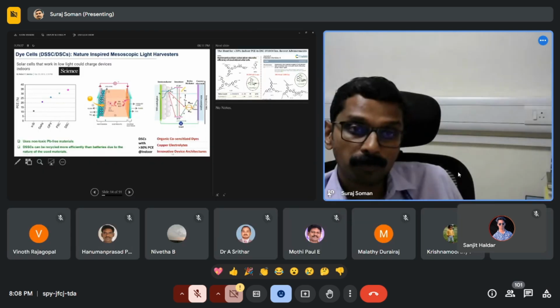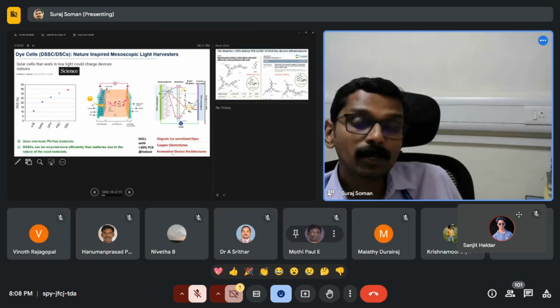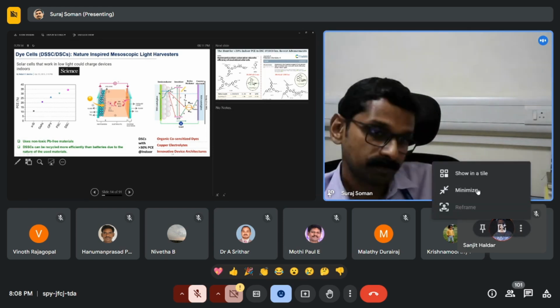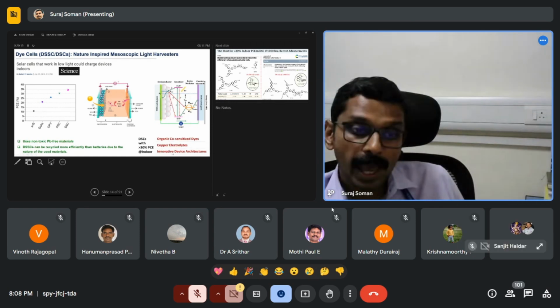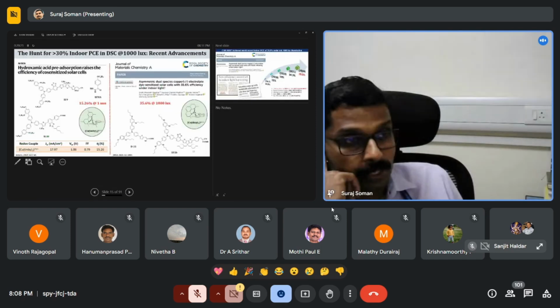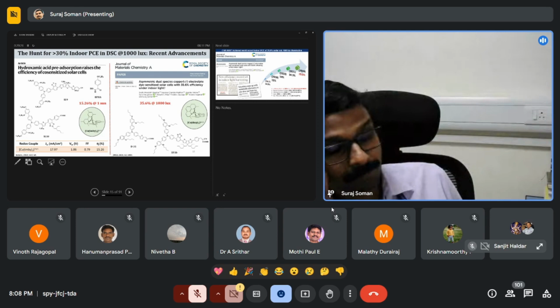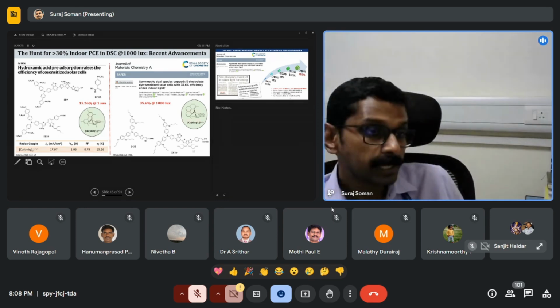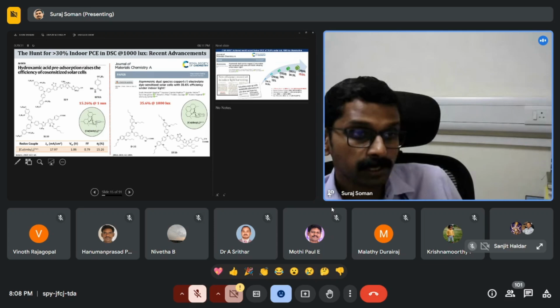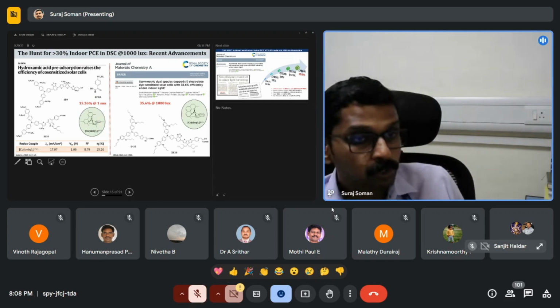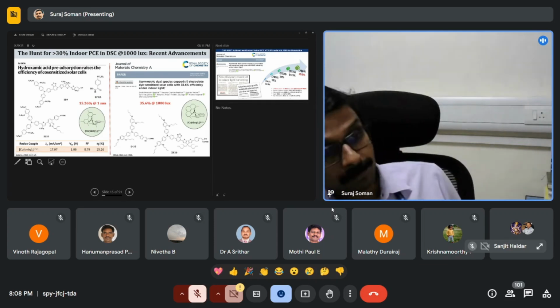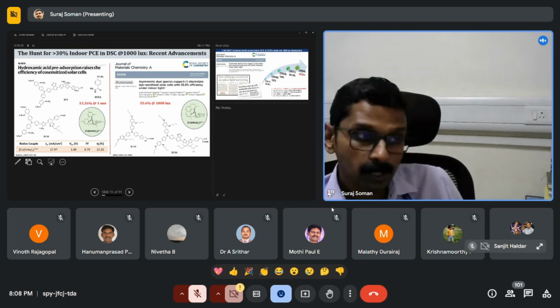That has been achieved by the use of organic co-sensitized dyes. The ruthenium-based conventional dyes were replaced by organic dyes. The conventional iodine electrolyte was replaced by copper-based electrolytes, along with the introduction of some innovative new device architectures. That has led to efficiencies of, let's say, the highest presently around 15% under one sun condition, and under indoor light somewhere around 35%, under the standard of around 1000 lux.